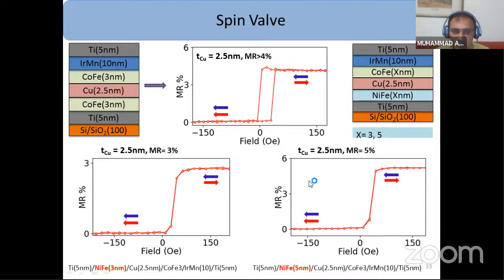This can be explained by the spin polarization of iron, cobalt, and nickel. That is one of the parameters for getting high MR, the dependence of MR on the spin polarization of metals. We know that iron has a better spin polarization than cobalt and then nickel iron. This is one of the reasons for getting the low MR value in the case of nickel iron.